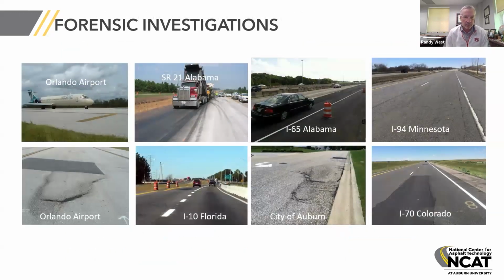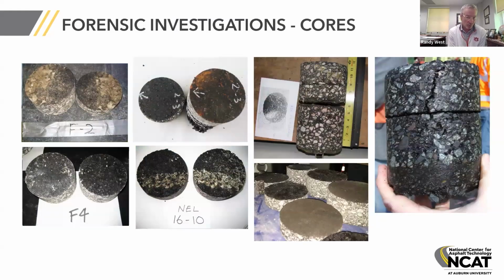Throughout my career, I've had the opportunity to be involved in a number of forensic investigations in Florida, at airports, on U.S. highways, in Alabama, a couple places, in Minnesota, in Colorado, to name a few. On those projects, we took cores as part of the forensic investigation and found delamination or debonding between pavement layers. And sometimes you can see that there is a tack coat there. You can sometimes see a little bit of a dusting. That dusting can be an indication that those layers are working against each other and creating a grinding process, and that's the sign that the failure is imminent. And then you see on the right hand picture there a crack that's developed in the surface from that debonding. So it is a common problem.